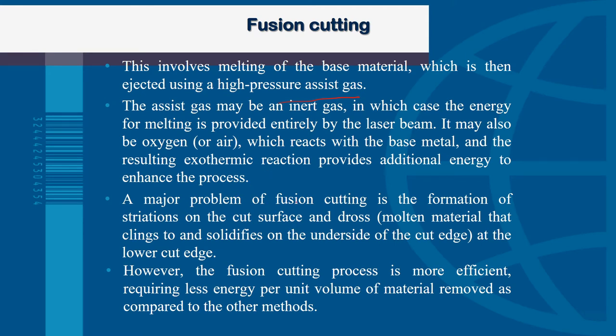The major problem of fusion cutting is the formation of striations on the cut surface, and dross, which is the molten material that clings to and solidifies on the underside of the cut edge. What it means by dross is that when you cut, you have a tiny amount of the material clinging at the base once the laser beam cuts the material. It is not so much when you compare to other cutting processes, for example, cutting with a bandsaw or even CNC cutting. The amount is just small.